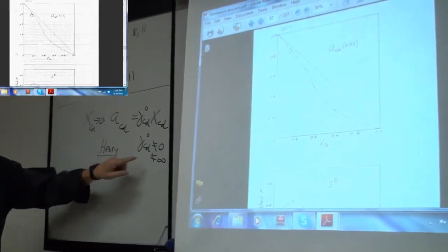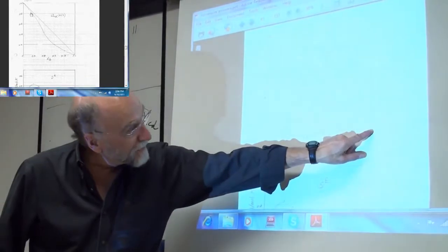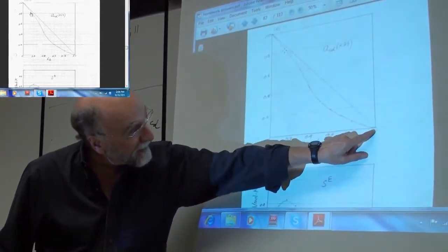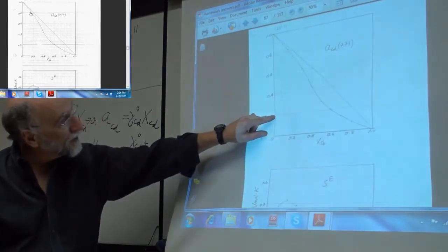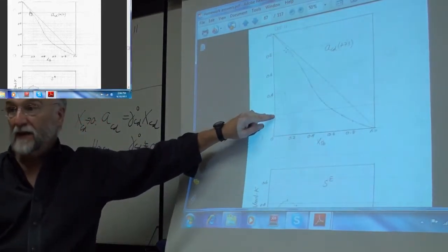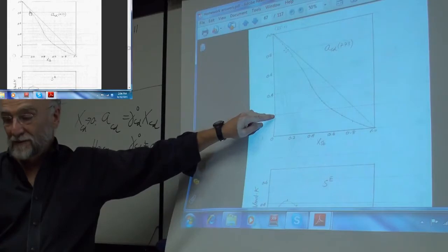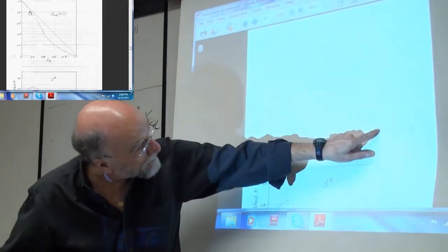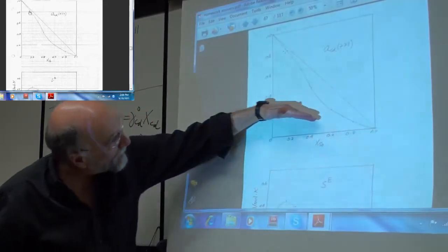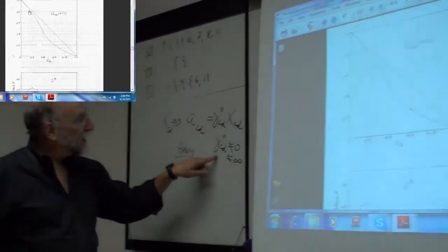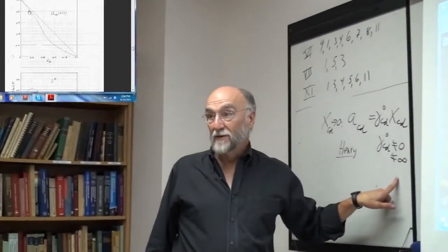That's all you're saying. So if you know the limiting value, gamma naught, if you take the limiting slope, if I took the slope of this line at the limit, at pure antimony, and made the tangent over here, then the intercept here would be the limiting activity coefficient. So I'll take the slope of this line at this endpoint and extrapolate the tangent out here. Then obviously this intercept is gamma naught cadmium when x cadmium is 0.